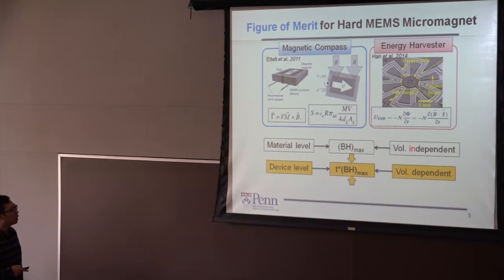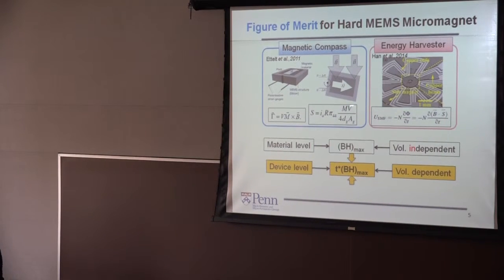Another example is a vibration-based energy harvester. The governing equation is well known, Faraday's law. The induced voltage depends on the rate of change of flux rather than the flux density. So B times S is similar to V times M, a volume-dependent property. So it's clear that on the device level, we really want a volume-dependent property. Given a constrained MEMS footprint, what we really want is large thickness and high energy density at the same time for a permanent magnet film.